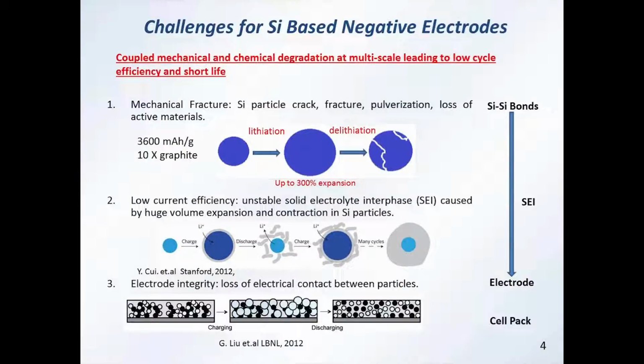However, there are several challenges for silicon electrodes that prohibit wide application at the current stage. The biggest issue is that while providing 10 times higher capacity than graphite, the volume change during cycling will be very significant. For example, during the lithiation process, the volume will expand more than 300%. And during the following delithiation process, the volume will change back to the original shape, which is another about 300% in theory.